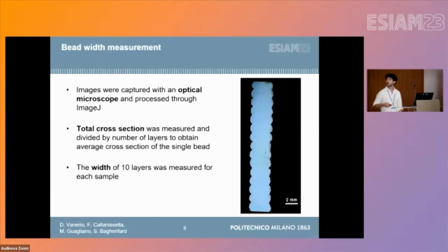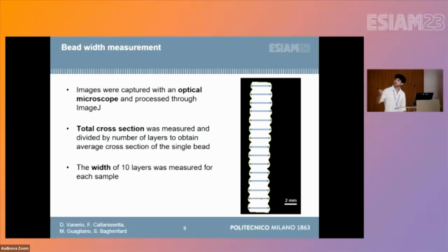From this, we went to the image analysis. We used a classical optical microscope. We first calculated the total cross-section of the sample, and then we calculated the cross-section of the single bead by simply dividing the total cross-section by the number of layers. And then we took 10 measurements for each sample for the width of each single bead.